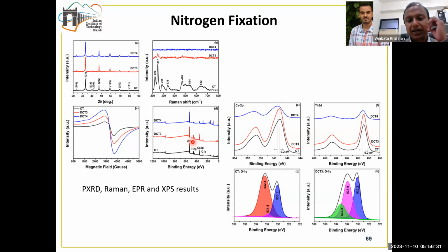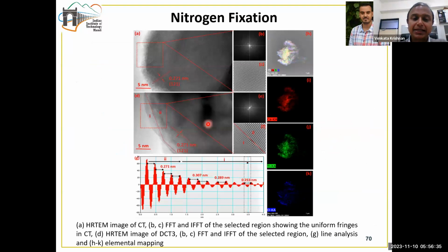And we have done a detailed XPS analysis and also a detailed HRTEM analysis, which also indicate the presence of the oxygen vacancies. We are able to identify the presence of the oxygen vacancies, but it is not easily possible to quantify them. But nevertheless, the identification is a good enough way.